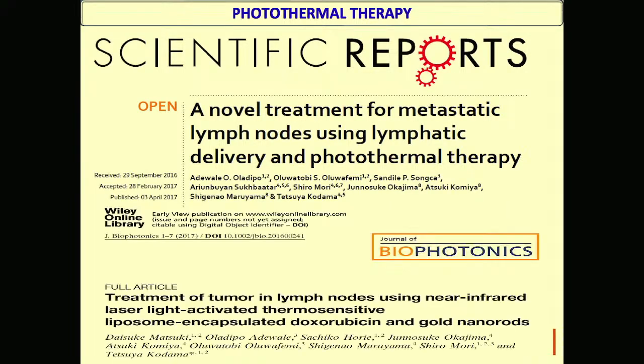And now, because we are having the challenge of how long it will take for our material to be approved by FDA, our collaborators suggested that we take some of the current chemotherapy drugs and see if we can reduce the amount by using this pathway. That is what we are able to do with some of them now. So instead of using something like 100 microgram per ml, with this pathway they only need 1 microgram per ml, and then they become very effective.